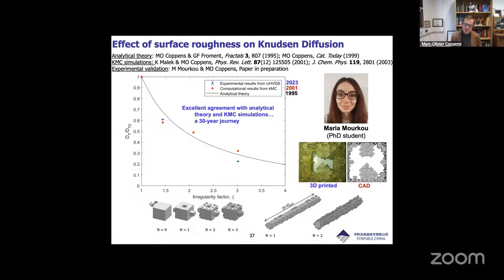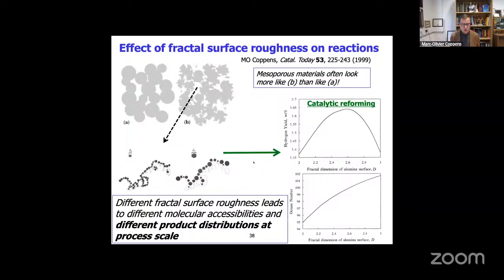So this to me demonstrates that it's really important to include this surface roughness, which was very hard to test directly on porous materials, because these disordered materials typically don't have all these parallel pores. So you have to include topological effects, and you may have other factors that play a role overall. The heterogeneity is difficult to control. So using a model like this can give us fundamental insights, which you can then use overall in pore network models. So does this really matter?